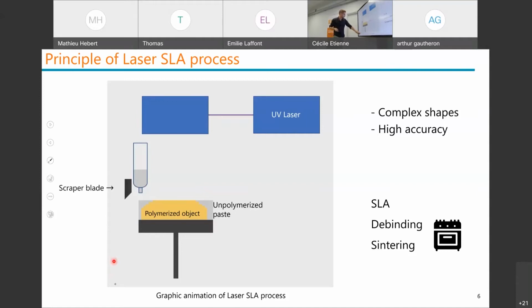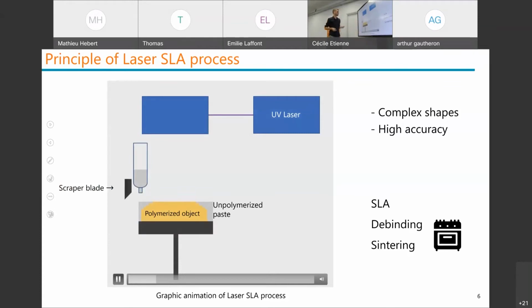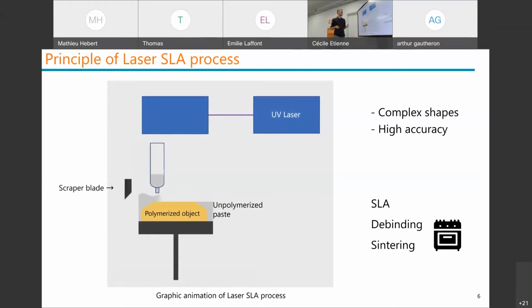show you the video. Okay. Like that. So there is a syringe. In it, you have a ceramic paste. It's made half of ceramic and also of other components like a monomer. So I spread the paste, and then the scraper ensures that the layer is very thin as we wanted and very regular, very flat. And then, as you could see, the laser is very fast and polymerizes the pattern I want on this layer. And I do it again and again.